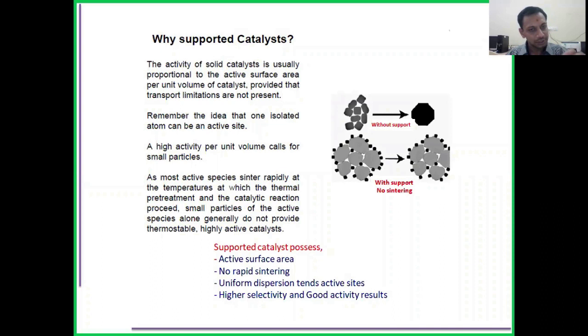So why a supported catalyst? As I just mentioned, with support no sintering occurs, because sintering is very dangerous in catalysis. Without support, you can see here all particles agglomerated. If all particles are agglomerated, then there will be no activity of the catalyst. With the support, we have a higher surface area and these black metal particles can easily be dispersed on the support, and we can get very good active sites for the reaction. An active site is like a seed. It can help to convert reactant to desired product if your system is optimized.